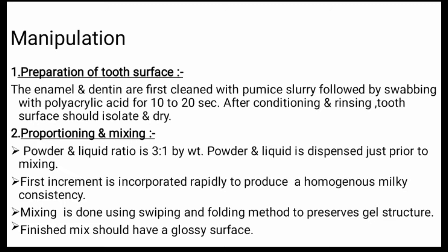For proportioning and mixing, the powder and liquid are used in a ratio of 3:1 by weight. The powder and liquid are dispensed just prior to mixing. The first increment is incorporated rapidly to produce a homogeneous milky consistency. Mixing is done using a sweeping and folding method to preserve gel structure. The finished mix should have a glossy surface.